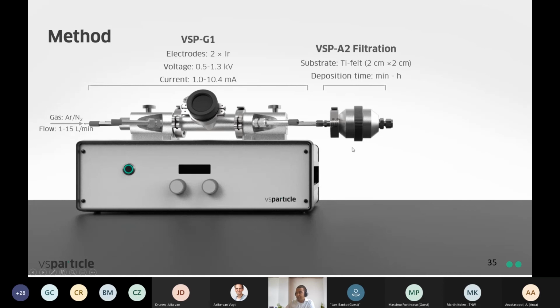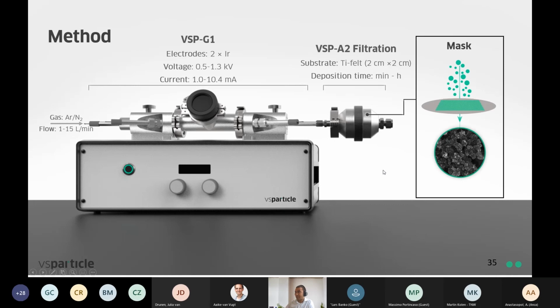liters per minute. And within the filtration accessory, they had their titanium felt as a substrate, and this is a 2 by 2 centimeter substrate that they used, and they varied the deposition time between a couple of minutes to a couple of hours. What was important here was their felt is square, and what we can do is we can just print a mask so that we can funnel these nanoparticles onto the felt directly. And this means that we're actually quite compatible with several different shapes and sizes of substrates that can be used in the filtration accessory.